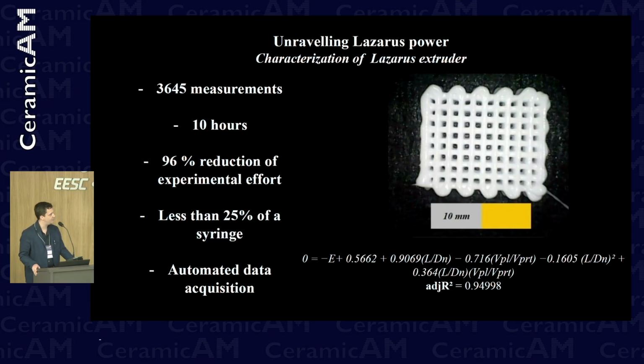So we made a model that combined Taguchi's design of experiments with dimensionless numbers, which are commonly used in heat and mass transfer calculations. And this model is highly efficient. We achieved a 96% reduction of the experimental effort necessary to optimize the model. We took 3,645 measurements in less than 10 hours and with minimal material consumption.